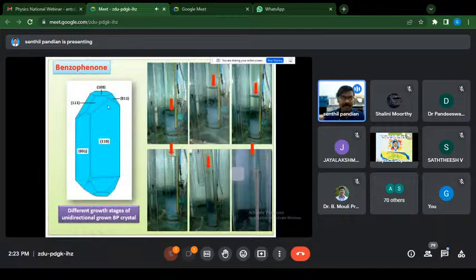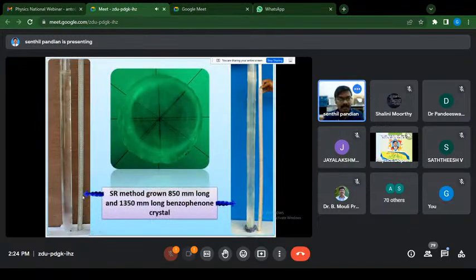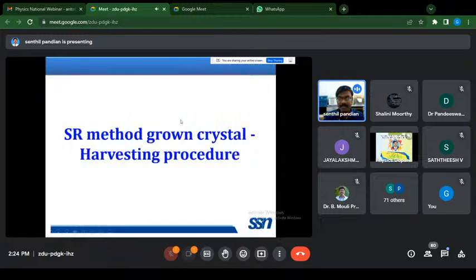This is the morphology of this benzophenone, and we have selected this 100 A direction for this longest growth because of the higher growth rate compared to the other B and C axes. So these are different growth stages of this benzophenone crystal. The seed crystal is mounted here, the roughness is started, then the transparent portion starts here. You see the crystal is growing. This is the 850 mm long benzophenone crystal. This is the 1350 mm long benzophenone crystal grown by this SR method. This is the double refraction pattern of this benzophenone crystal. The total thickness of this crystal is 5.5 centimeter.